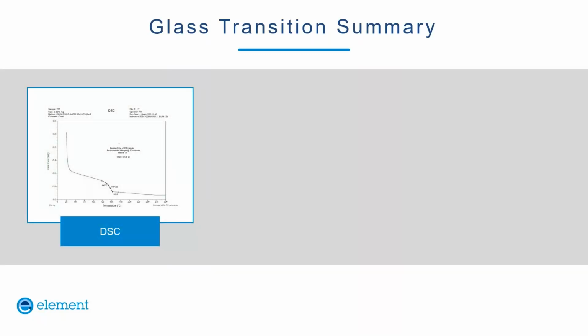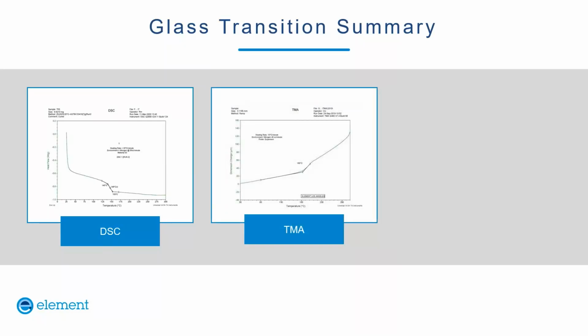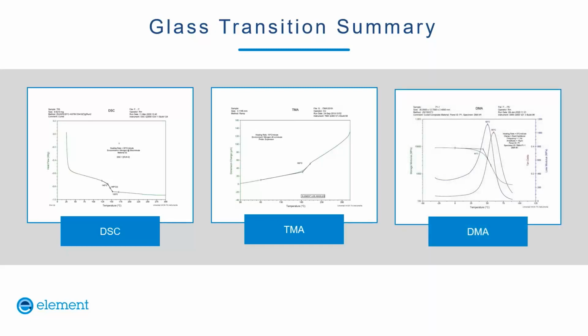So the three most common ways to measure TG are DSC, TMA in the expansion mode, and DMA. And we've looked at all these curves, and now you can see how the TG is apparent. Dielectric spectroscopy is another way you could measure TG, but the methods haven't really been standardized well enough to be in general use in industry. It's more a thing of academic interest and also for cure monitoring.